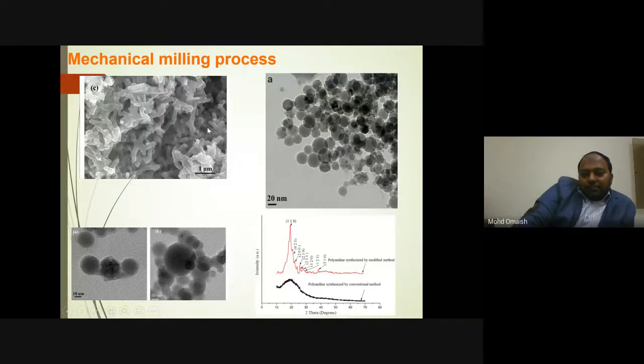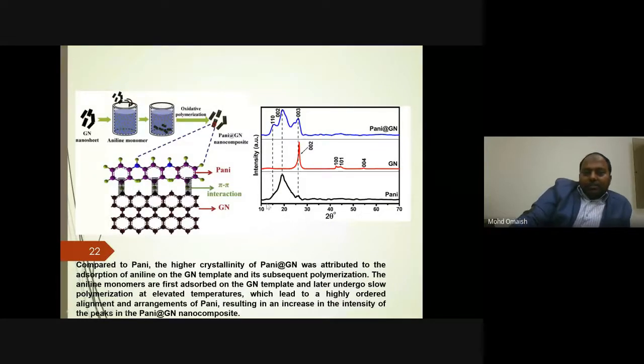Apart from morphological analysis, one of the most important factors in polyaniline is the temperature at which you do the polymerization. Here we polymerized aniline at a much higher temperature, above room temperature, and this slow polymerization gave very good crystalline polyaniline, in contrast to the amorphous polyaniline we get in normal conventional polymerization. Apart from this, we can use nanoparticles for adsorption of aniline. For example, here we used graphene for adsorption of aniline, and consecutive polymerization can give very good crystalline features.